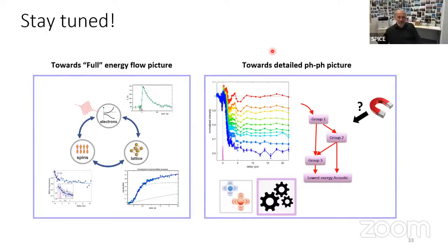So maybe I can comment, Massimo, also, since that's something that I'm a bit of an expert on: the anomalous Hall effect. Essentially, the Berry curvature is connected to the anomalous Hall effect and XMCD, which is essentially the X-ray version, or the finite frequency version, of the anomalous Hall effect. By symmetry it is allowed, because you have an axial vector in your system, the magnetization, so you will have a response in the XMCD as well as the anomalous Hall effect in DC transport.